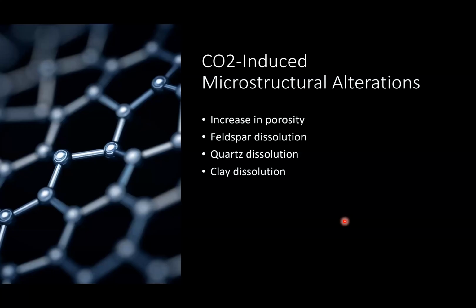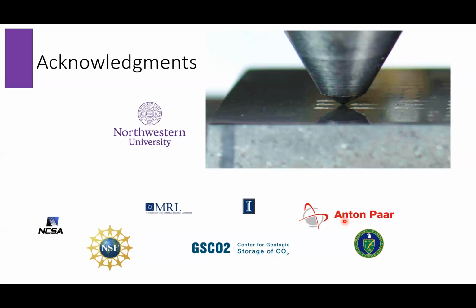So let me summarize what we've learned: as a result of incubation in CO2 saturated brine, we're going to have an increase in porosity. We're going to have dissolution of feldspar, dissolution of quartz, and we're going to have dissolution of clay. This is what we've learned. And those microstructural and compositional alterations are going to lead to a decrease in mechanical properties.